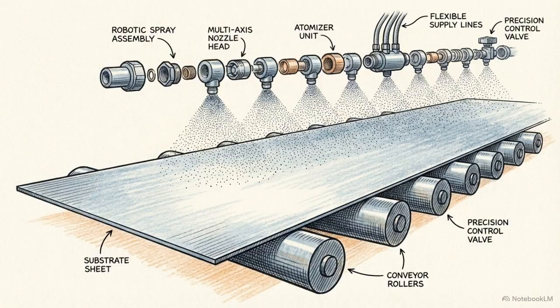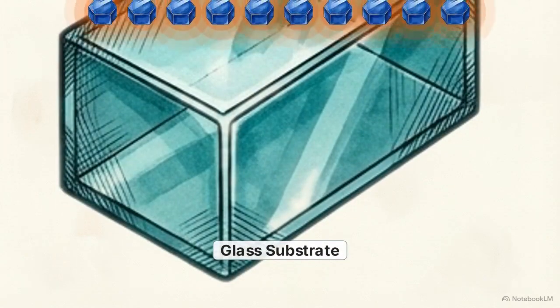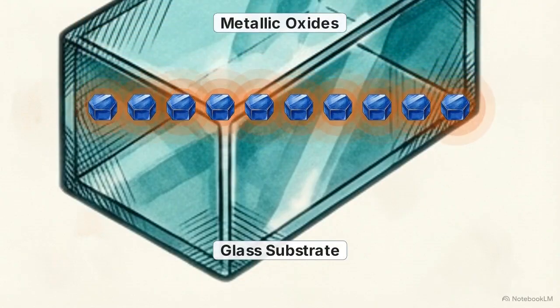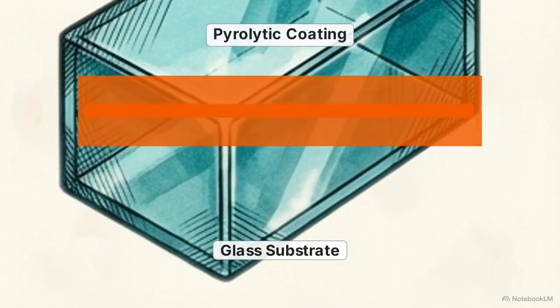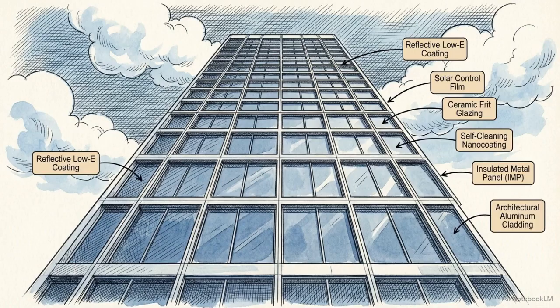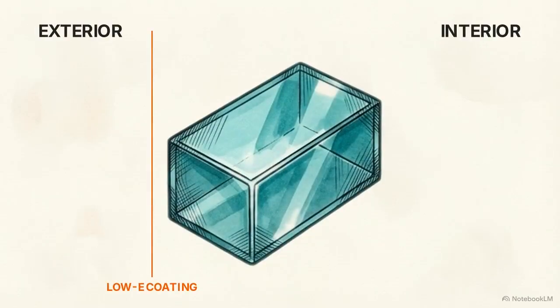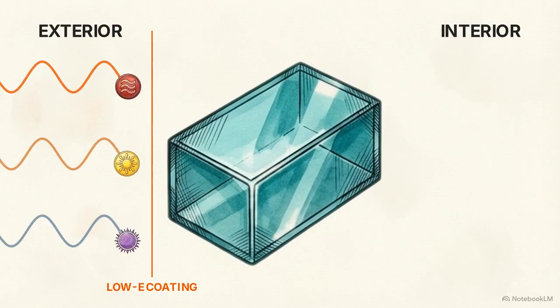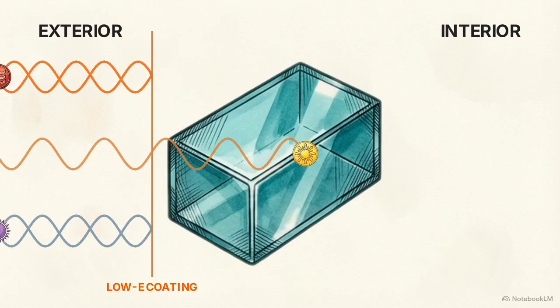Because the float process is continuous, manufacturers apply pyrolytic hard coatings directly on the production line. Pyrolytic coatings are microscopically thin layers of metallic oxides bonded directly to the glass surface at extremely high temperatures. These metallic oxide layers create advanced architectural products like self-cleaning windows and low-E glass. Low-E stands for low emissivity. The coating minimizes ultraviolet and infrared light passing through the pane, providing excellent thermal control for buildings.